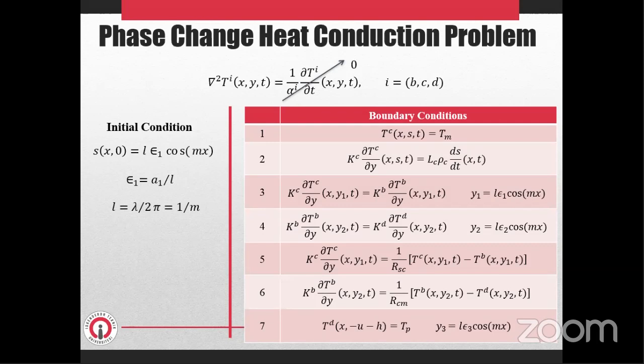Heat flux from the casting to the coating and coating to the mold is moderated by the thermal contact resistances RSC and RCM, as described by the boundary conditions in equation 5 and equation 6, due to the presence of air gaps and inclusions of materials of poor conductivity at the interface. And lastly, equation 7 prescribes the boundary condition related to constant temperature of the mold outer surface.